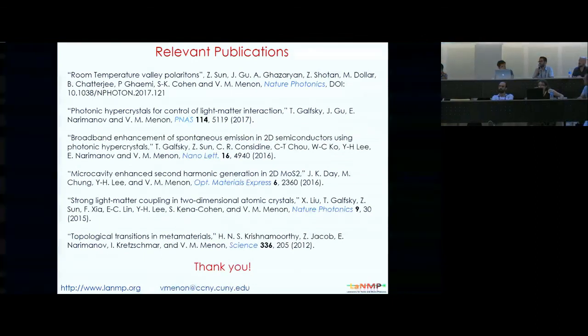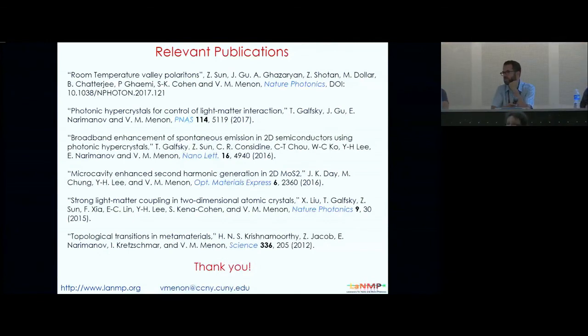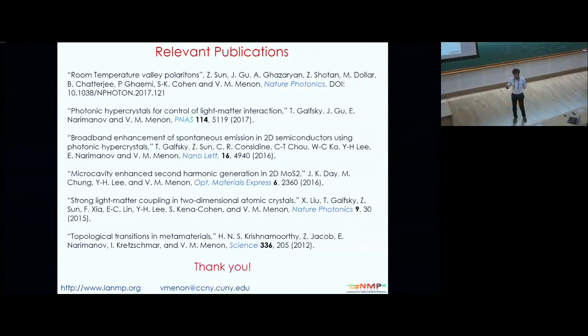Irradiation? Yes. The original paper that I showed was from Igor Aharonovich's group in Sydney, and they have done some electron irradiation to try to do it. Dirk Englund's group has also tried something along those lines with ion implantation. That's another approach one can take. The other way to do this is you can just take this material and anneal it at 850 Celsius, and that activates the color centers. But again, you don't know where they are going to happen.